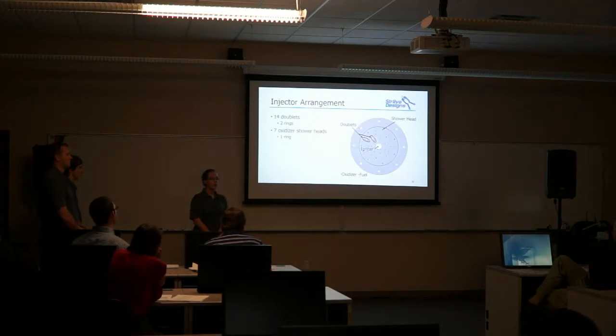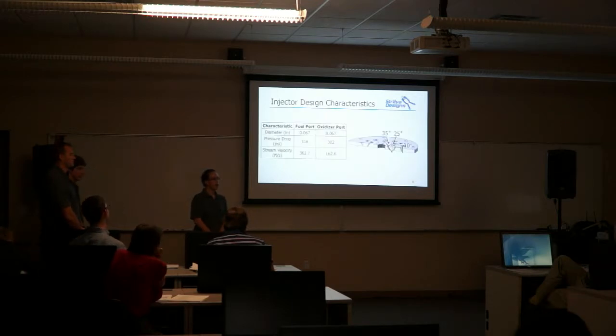The image you can see on your screen is the injector arrangement that we have determined. We have gone with 14 doublets arranged in two concentric rings of 7. We also have 7 oxidizer showerheads in a ring around the perimeter of our injector plate. Both the fuel and the oxidizer ports are at 0.067 inches in diameter. We have also designed both of these for an approximate pressure drop of 300 psi. This is 30% of our combustion chamber pressure and is on the higher range of this ratio. We did so to allow us to draw back the mass flow during throttling and still maintain combustion stability.